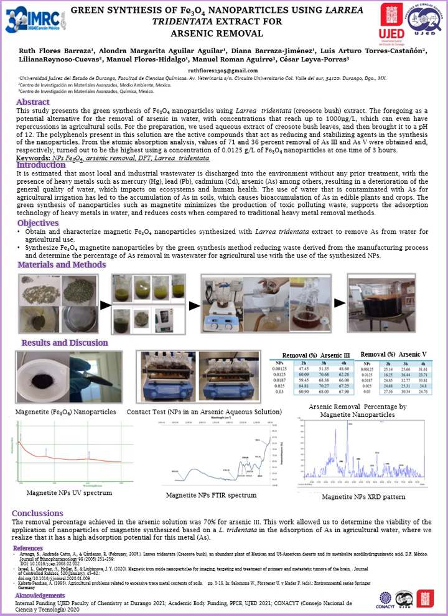In another flask, 20 milliliters of the salts and 30 milliliters of the creosote extract are added while still stirring, taking on a dark color indicating the formation of magnetite nanoparticles. A solution of sodium hydroxide was added drop by drop in such a way that we adjusted the pH to a value of 12. After this process, the nanoparticles are washed with deionized water 2 times and another 2 times with ethanol.